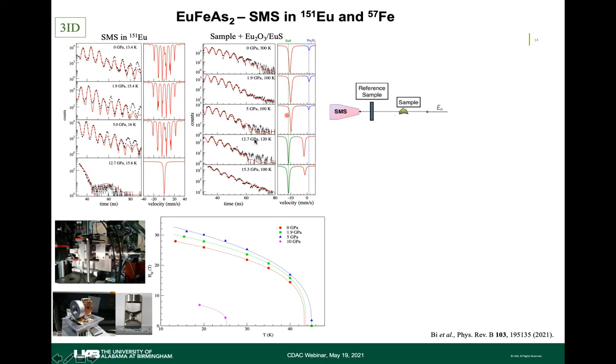And above 5 GPa, for example at 12.7 GPa, the isomer shift is very close to 0. So if we keep using the 3+ standard, we wouldn't see much feature in the time domain data. So we switched to the 2+ standard. So this energy separation is larger, which gives more oscillation, faster frequencies in the time domain.